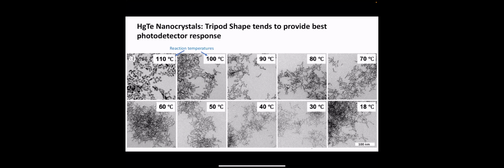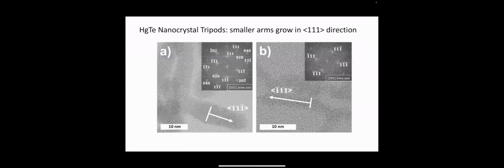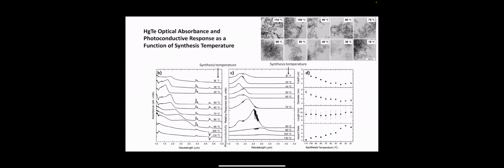So maybe 3 hours, but it's not like 2 days or anything like that. And so these are some of the 1-1-1 arms. You can control the optical gap pretty easily in the shortwave infrared and the midwave infrared. Going to the far infrared becomes a little more challenging, or at least to get decent